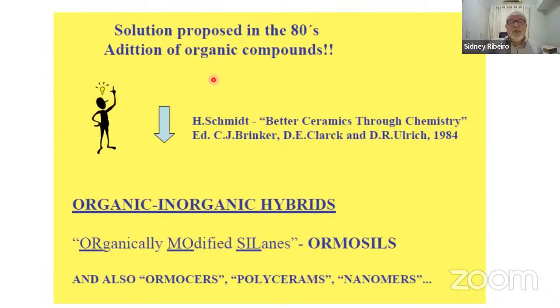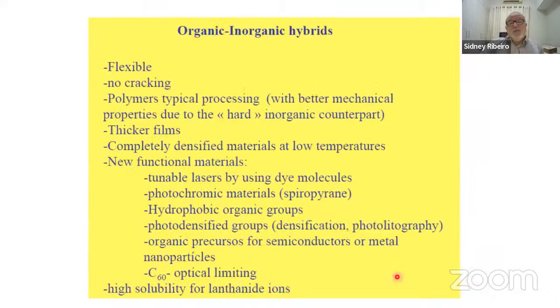The solution proposed is the addition of organics. So this is the work done by Helmut Schmidt in Saarbrücken in Germany. These are the so-called organic-inorganic hybrids, ormosils, from organically modified silanes. In the literature, these materials are also called ormocers or polycerams or nanomers, a lot of different names for them. And these materials are wonderful because you have both the good parts of the organic and inorganic worlds. So they are flexible, there is no cracking, they are processed like polymers. You can obtain thicker films, completely densified materials at low temperatures, and you can think about new functionalities.